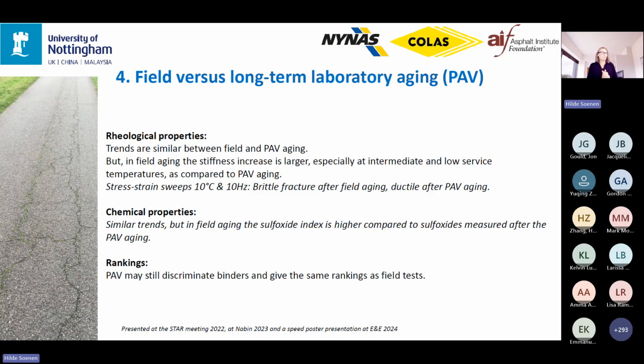So I come now to the conclusions of this section. As mentioned, regarding rheological properties, the trends are similar, but in field aging, stiffness increase is larger, especially at low and intermediate service temperatures, and these are just the temperatures where we get pavement cracking. We also did stress strain sweeps, which I do not show you in this presentation, but we saw brittle fracture after field aging and ductile behavior after laboratory aging.